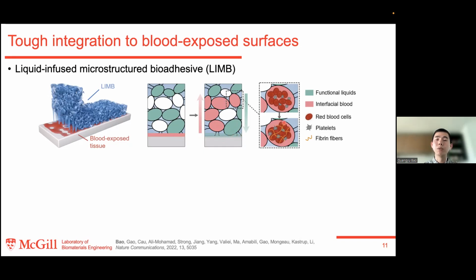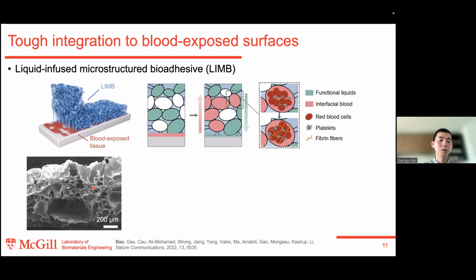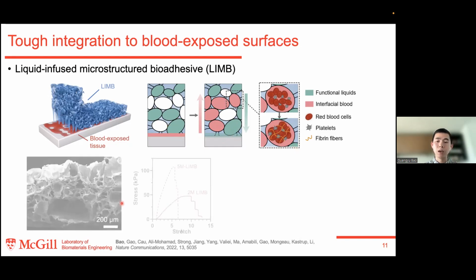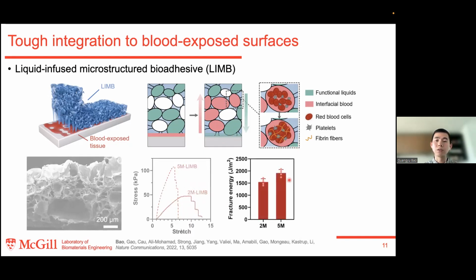The absorbed blood within the matrix can be further coagulated to form a blood clot, which can further enhance the sealing effect. And here is the SEM image showing the porous structure of the bioadhesive matrix. Although they are highly porous, they are still very stretchable, and can be stretched at least 6 times their original length without rupture. And the toughness is also very high.